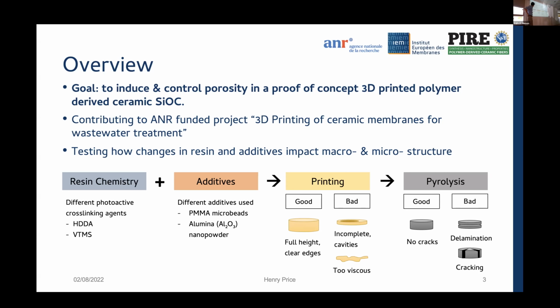And so the testing I conducted was seeing how changes to the resin system, as well as additives, which are other materials added to that liquid resin, impacted the macro and the microstructure of these samples. So resin chemistry plus additives, and then the evaluation that I conducted was after printing and after pyrolysis.